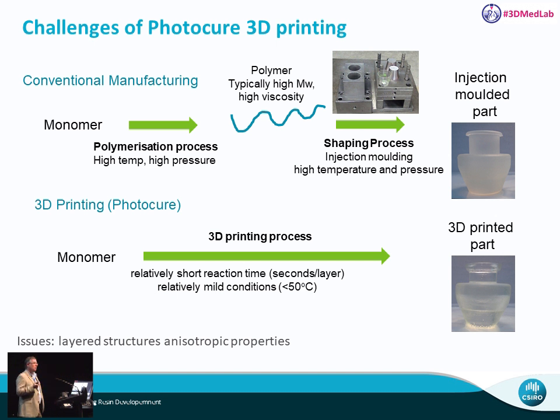So if we think about how conventional plastic parts are made, it often involves a two-step process, and the starting point is often a monomer. This is the basic building block of a polymer, and we do a polymerization process, which is often done at high temperature and high pressures, and that generates our high molecular weight polymer. It's typically a solid or at least a viscous liquid. And then we do some secondary process to shape it. That might be something like injection molding, and you might need some metal tooling. And again, you're using high temperature and high pressure to eventually make a part that you want.